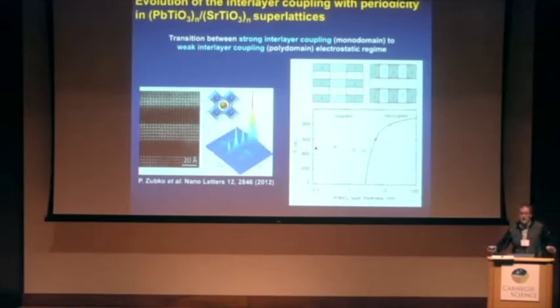However, if we start to increase the number of layers of the dielectric, the energy that you have to pay to polarize strontium titanate increases, and at some point, you cannot afford it. And in that particular case, the system has to choose between reverting to a paraelectric phase or breaking into domains that are confined in the ferroelectric region that are now electrostatically decoupled.